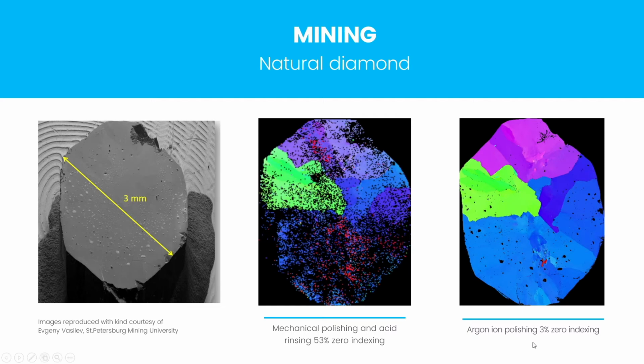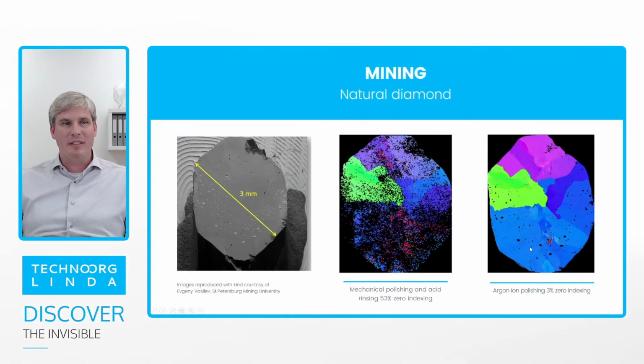But after some minutes of ion milling, actually 100% of the area was indexed. Actually, you see 3% of zero indexing here. That's because there are holes in the sample. So where you have no material, you have no signal, obviously, but all the other parts were indexed, including every single area of that sample.